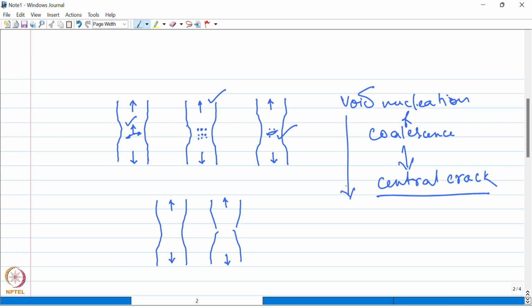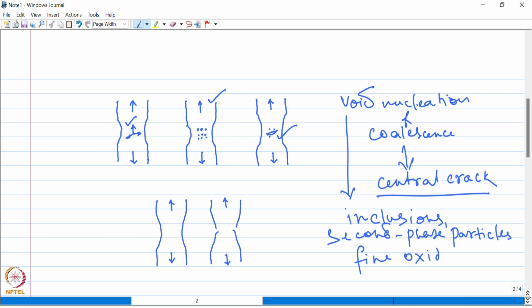And when you talk about void nucleation, voids generally form at sites like inclusions, second phase particles, or fine oxide particles present in the material, and also at the grain boundary triple points.